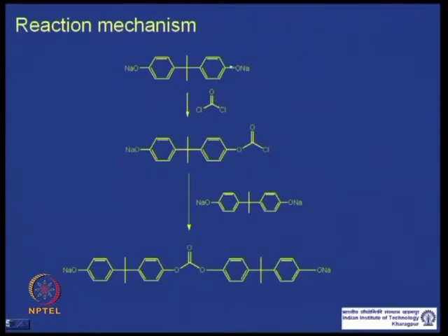You have BPA present in the aqueous sodium hydroxide solution, so you have the phenolate salt. At the interface this reacts with phosgene forming this compound, which on reaction with bisphenol A salt will form a dimer, and the reaction proceeds further in this way.